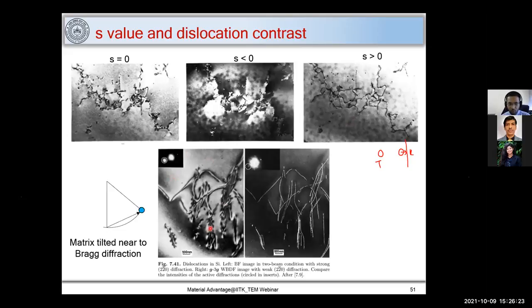Here I have marked the two beam condition, and here I have marked a weak beam dark field condition. Here in this case, I can resolve each dislocation properly. So you should not always go for a two beam condition. Rather, you go for a weak beam dark field condition to image dislocations.